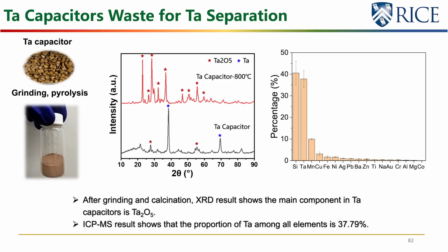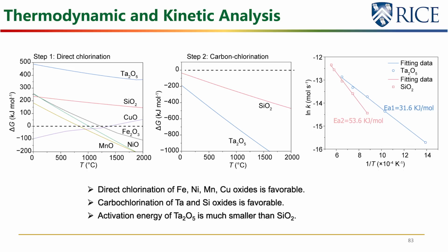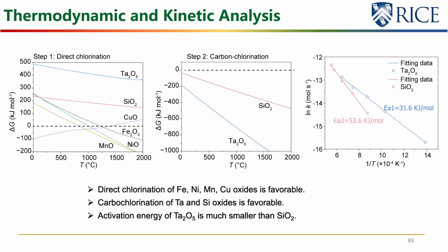Then we take that with other metals, so it has a number of other metals. So we get the tantalum oxide after calcination, silicon oxide, copper oxide, iron oxide, nickel oxide, and manganese oxide. And now if you just do a direct chlorination, you heat them up with a flash Joule heater, just the thermodynamics, this is just the modeling, it's very simple on commercial software. When delta G is less than 0, it's a favorable reaction. Silicon and tantalum don't chlorinate directly at any temperature along this profile. Whereas all the other metals there, if you do the flash right here at about 1250, all these other metals are going to chlorinate and come distilling out. And that's going to leave just silicon and tantalum.